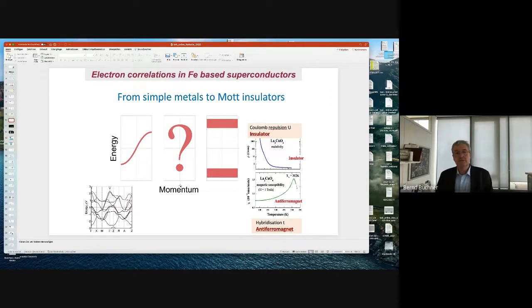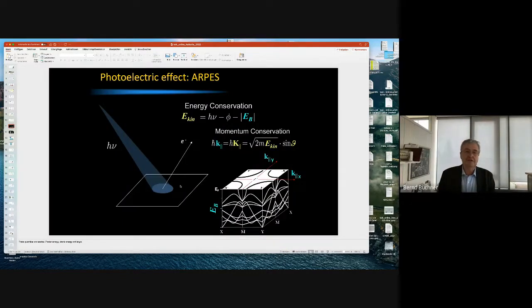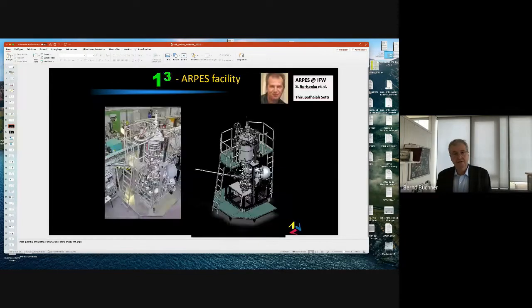And in order to address this point, we did photoemission spectroscopy. That's just a reminder. So we shine light on the samples. Electrons leave the samples, and there is energy conservation and there's momentum conservation, at least for 2D systems. And this allows us directly to measure the band structure, to measure the electronic structure of these systems. And this is done a lot at our institute, and Sergei Borisenko is one of my group leaders, and there's a big machine which is located at a synchrotron facility where we can do among the highest resolution measurements of this technique possible in the world.